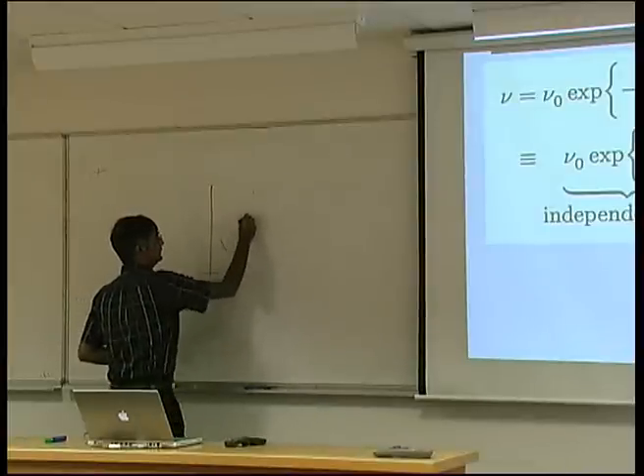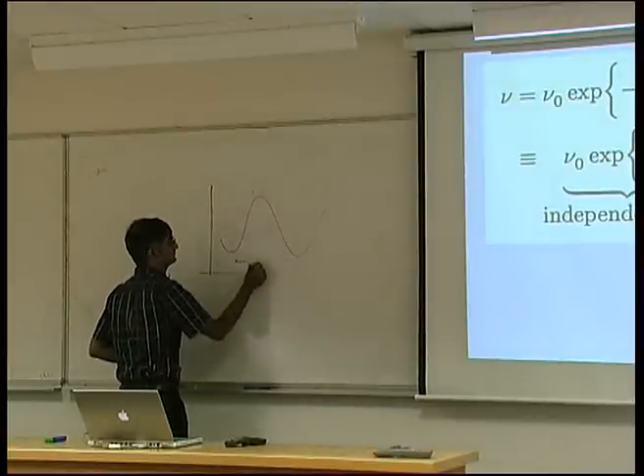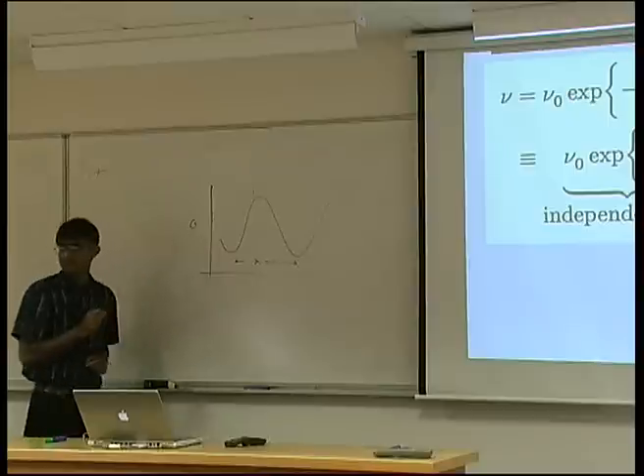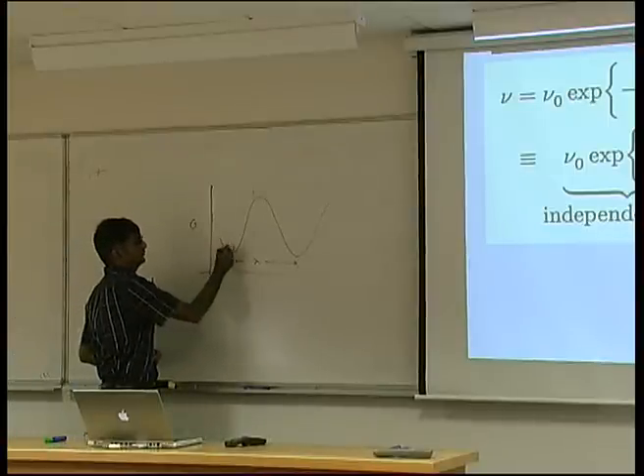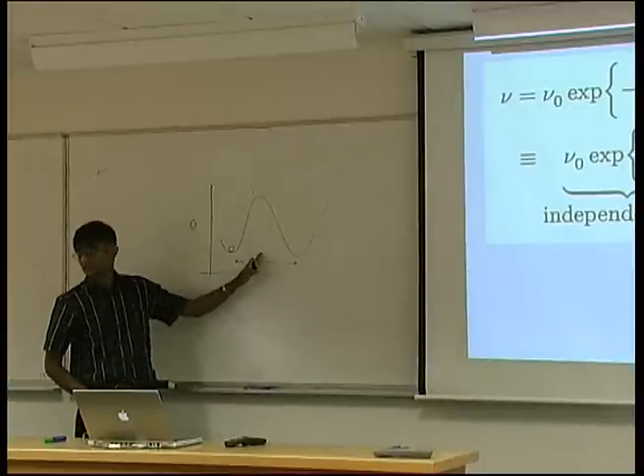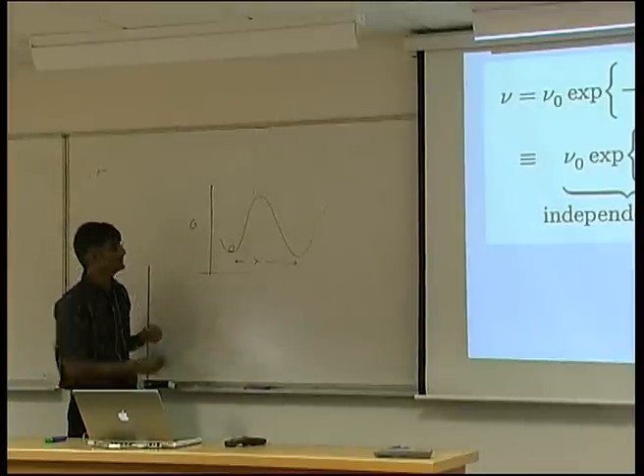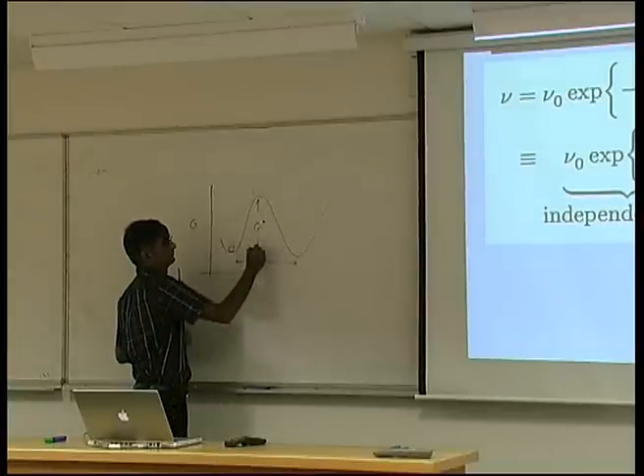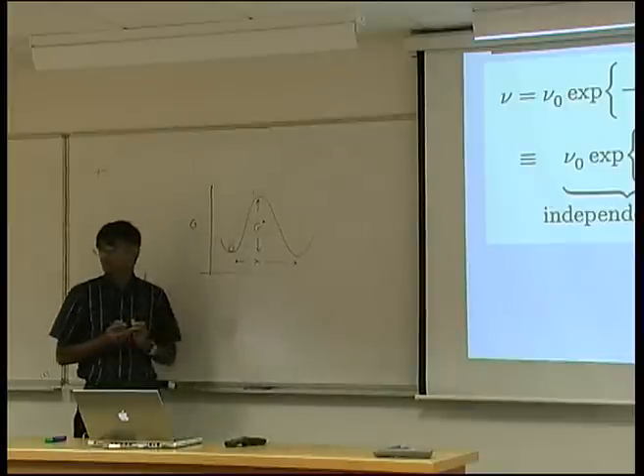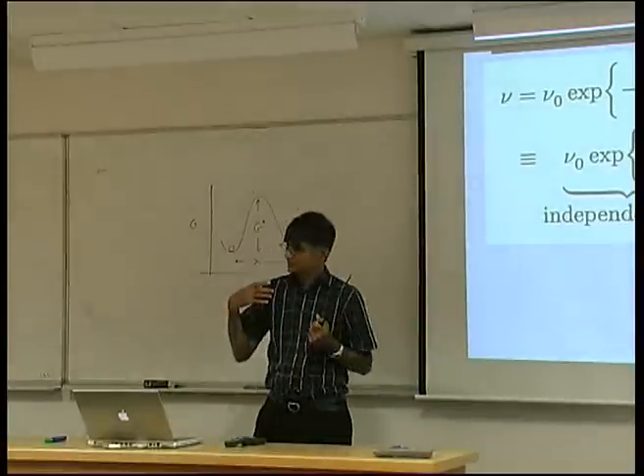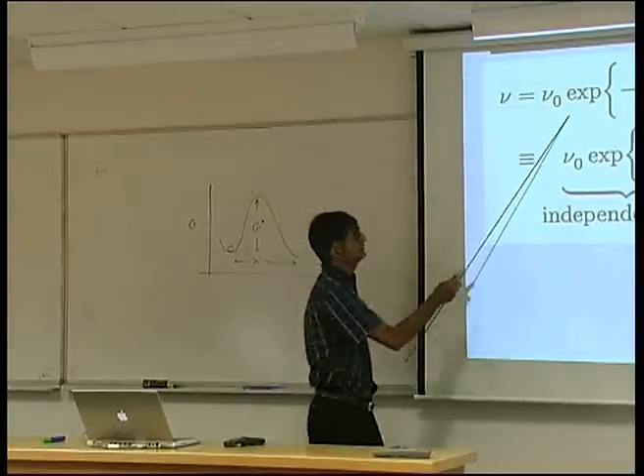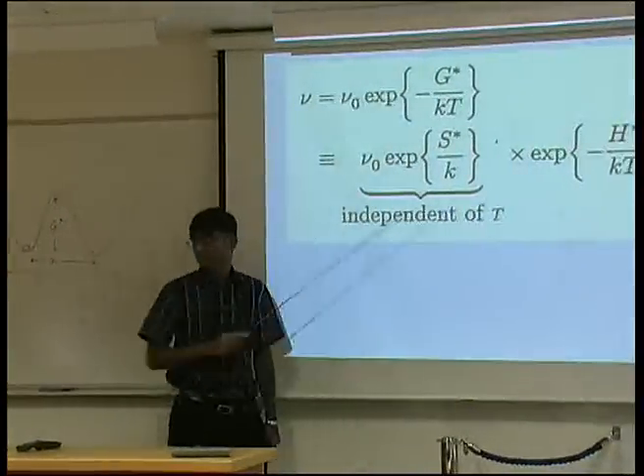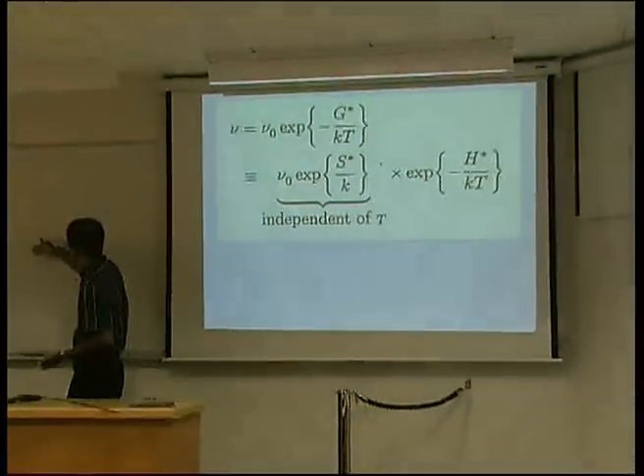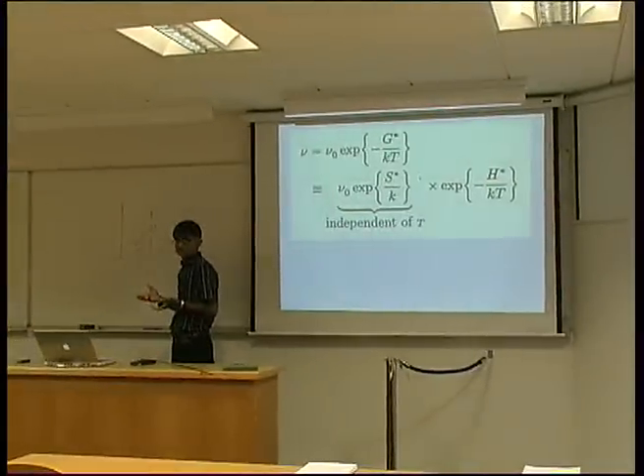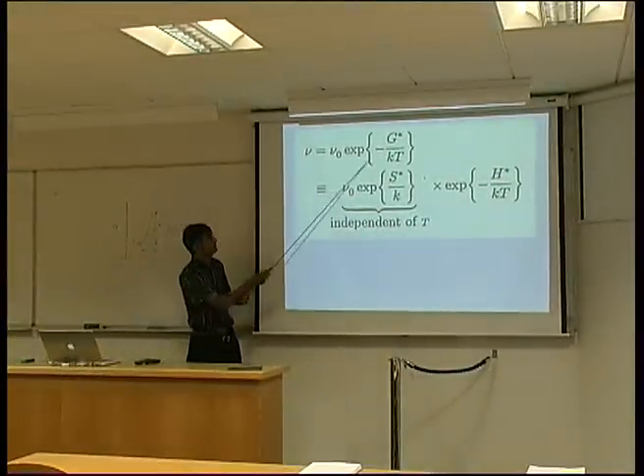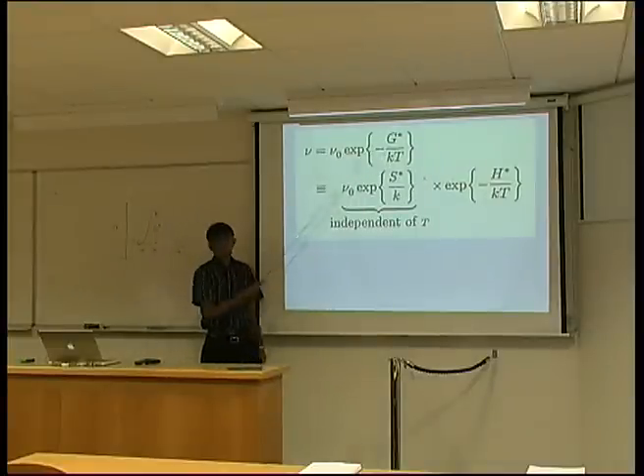So if these are the equilibrium positions here, and free energy being plotted here, if an atom wants to go from this position to this position, it's got to push past other atoms, and therefore it has to cross this barrier, G star. It's vibrating all the time, and sometimes it will be successful in overcoming that barrier, and the probability of a successful jump is e to the minus G star upon KT, because the excess energy that it requires in order to get over this bump comes from thermal vibrations. So this is simply the probability of a successful jump, G star over KT.